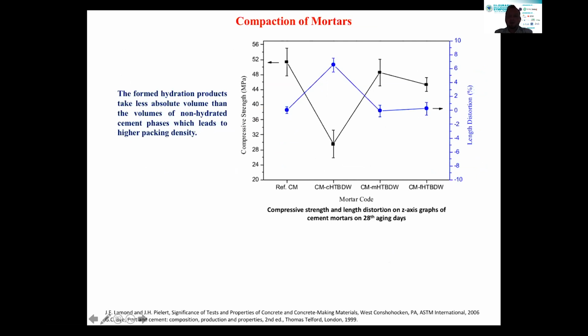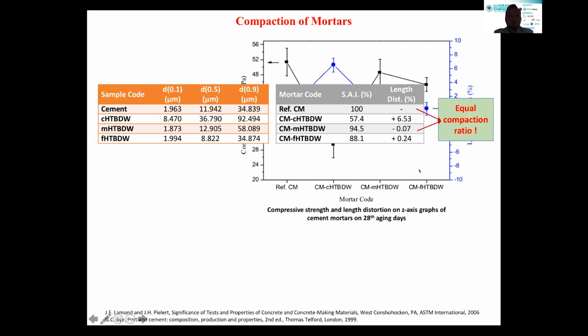We measured the length distortion of cement mortars on the z-axis after the 28 aging days. Briefly, you can see the values here. An expansion occurred for the coarse powder with the much broader particle size, and the reference mortar and the medium waste incorporated mortar have similar length distortion. It means an equal compaction ratio, and it shows the availability for the application.